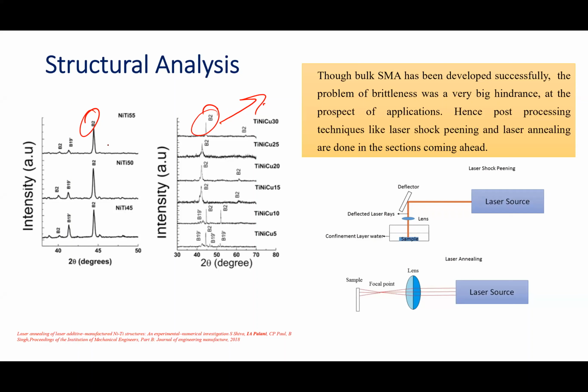But when we fabricated the structures and put them in the field, within no time a breakage was observed, because the results say there is quite a good amount of brittleness. In order to avoid that, when we investigated, we could understand that there was some non-uniformity in the structure. This non-uniformity is happening because of the exothermic reaction generated between the NiTi and Cu structures. Because of this, there was some amorphization here and there. In addition, there was some residual stress generated in that region.